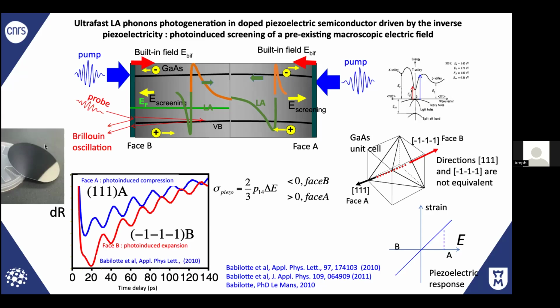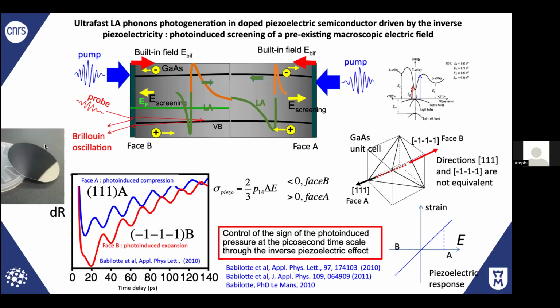And what do we see? When we shine light and excite, there is an electronic signature first, and after that we see oscillations like that, which are typically the coherent acoustic phonons. And if we look at the signal on phase B or phase A, they are opposite. It's just due to the fact that the piezoelectric effect can be reversed. You can control compression or expansion. So with the light, you can really control the lattice motion.